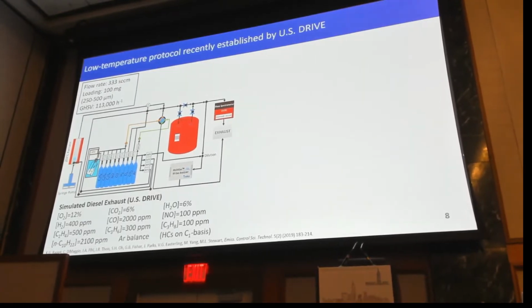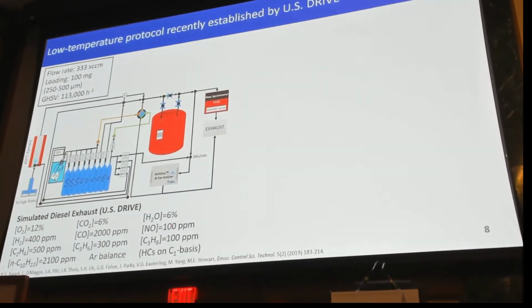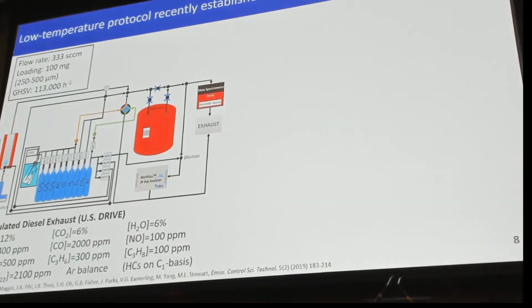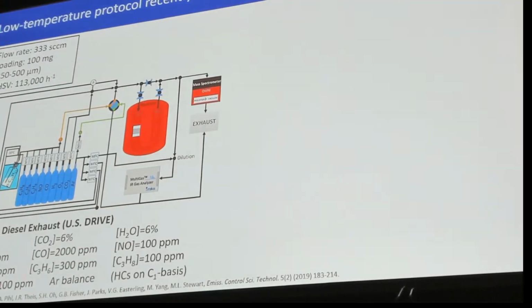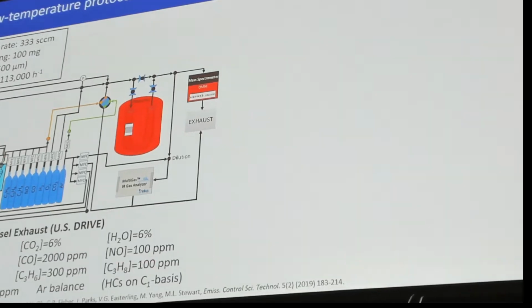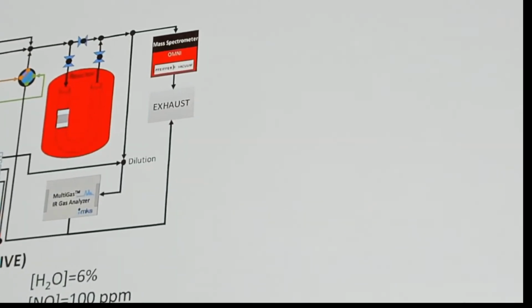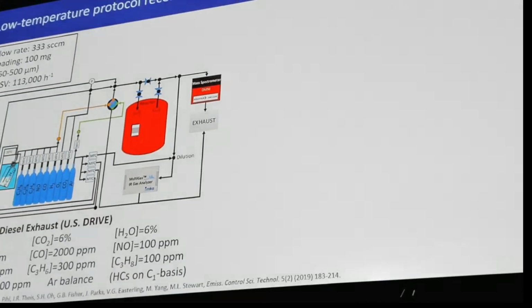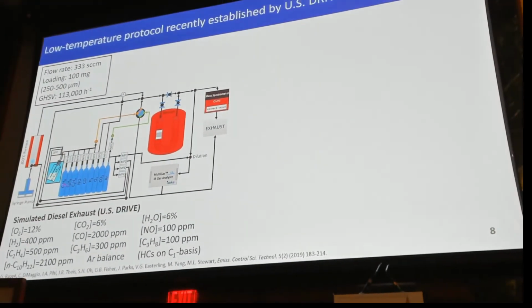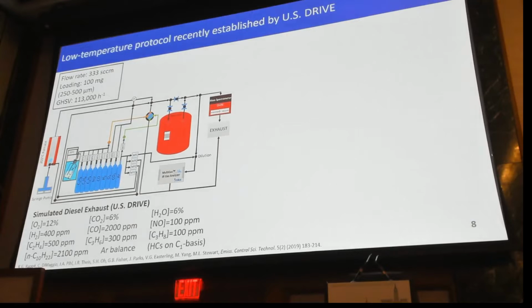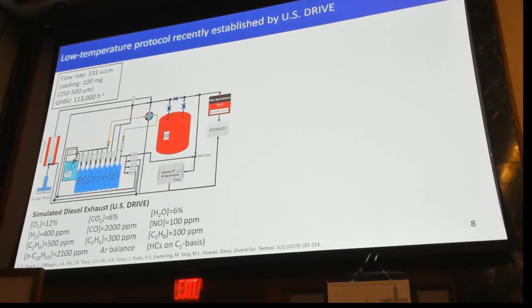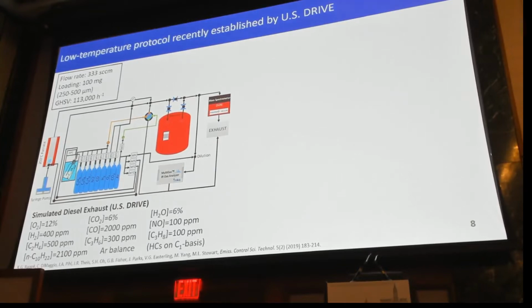So we flow oxygen, we have CO2, we have 6% water, hydrogen, CO, and NO, and we have 4 hydrocarbons: ethylene, propylene, propane, and decane. Water in our reactor is introduced with a syringe pump, and the liquid decane is introduced with a bubbler that is immersed in a water bath at a controlled temperature. In this case, the temperature is 20 degrees C.